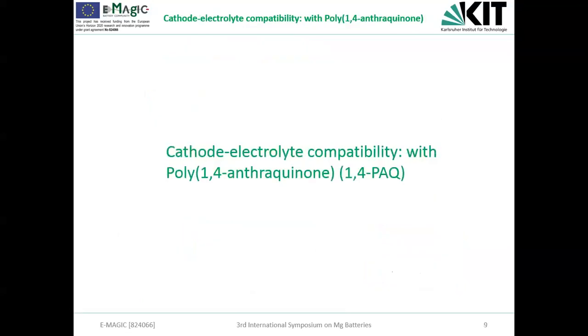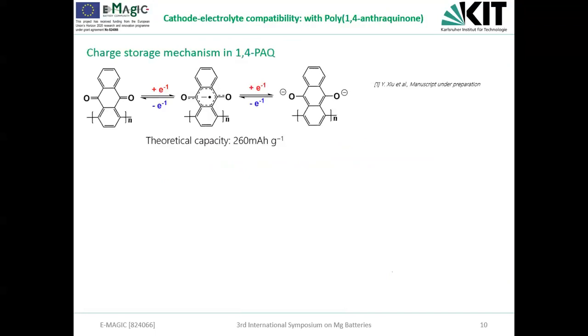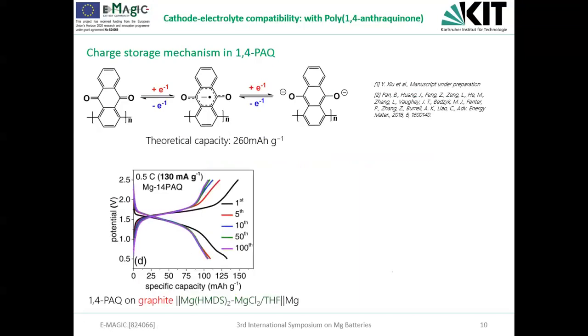So with this successful compatibility test, we also tried another cathode which has a higher capacity and also a higher voltage. Here I want to present this polymer cathode, the polyanthraquinone structure. Basically, the charge storage mechanism of this material relies on the redox of these carbonyl groups. If we consider both carbonyl groups involved in the reaction, we have a theoretical capacity of 260. But in the practical case, as reported previously, the accessible capacity is only around 110, which is less than half of the theoretical value.